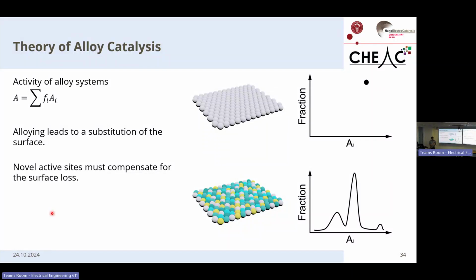But now as we start to alloy it, we add elements that are going to perturb these activities and increase the activities of these active sites. So we form an activity distribution which now looks like something like this. Our most active sites shift up in activity, but at the same time we have introduced ligands, and these ligands are not necessarily active towards the reaction, but they still occupy the surface. So we end up also with a fraction of inactive surface, which we can assume to be dead. So an alloy is only competitive with its counterparts if it can compensate also for the loss in surface. And in a random system, this distribution is governed purely by statistics. So we can construct a statistical model to evaluate these activities that alloys need to have in order for them to be competitive with their counterparts.